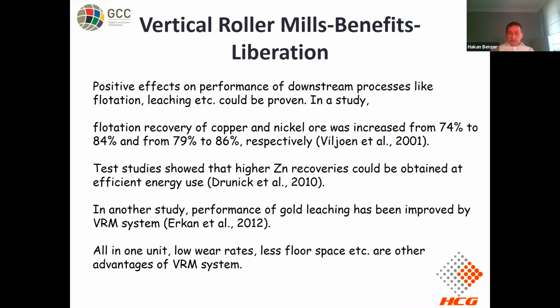Again, this study comes from our gold application. We measured higher gold leaching performance when we implemented a VRM system. The reason is that the microcrack propagation is immediately utilized by the downstream process. In this system, we do not have any other comminution process which kills the microcracks created by the high compression system. So everything is in one unit.